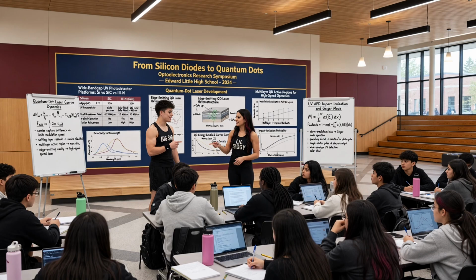The principle states that no two identical fermions, like electrons, can occupy the exact same quantum state simultaneously. It's like trying to park two cars in the exact same parking spot. Makes sense. When that extra free electron falls into the dot, it occupies the lowest available energy state. Now, the dot is no longer neutral, it is charged. It has formed what is called a trion state, 2 electrons and 1 hole. And how does that stop the fluorescence? Because the dot is now negatively charged, the Coulomb force, the electrostatic repulsion between the newly trapped electron and the electron our laser is trying to excite, causes the fundamental energy levels of the artificial atom to shift slightly.